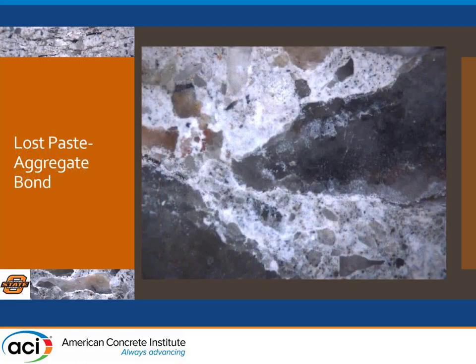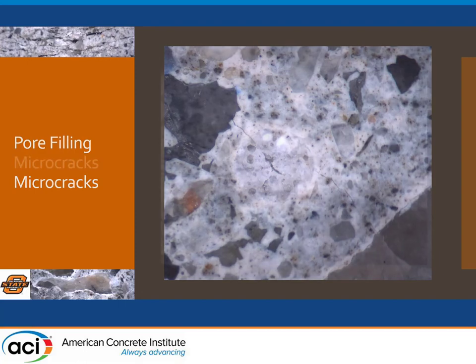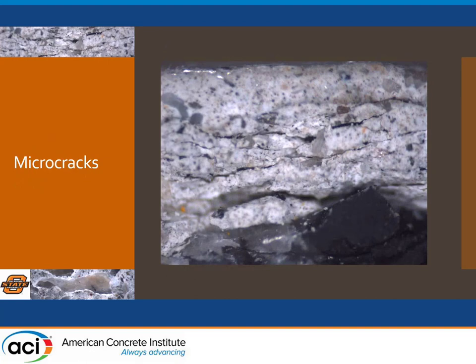As this progresses, we start losing cohesion around the aggregates, and then we have loss of paste and aggregate bond, which starts affecting the mechanical properties of our concrete. The sulfate products try to find every nook and cranny to form and expand — for example, air voids become completely filled with sulfate compounds. This causes expansion-induced cracking, which progresses into a network of micro-cracks that will eventually completely deteriorate the material if the attack continues in contact with the source.